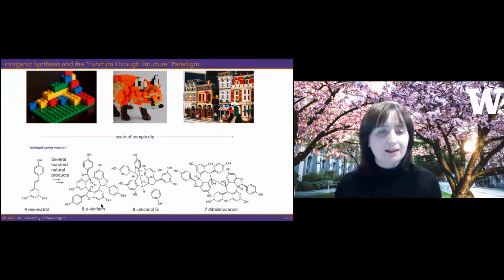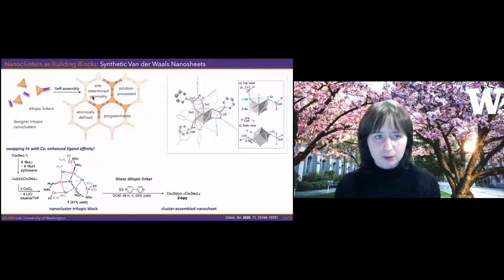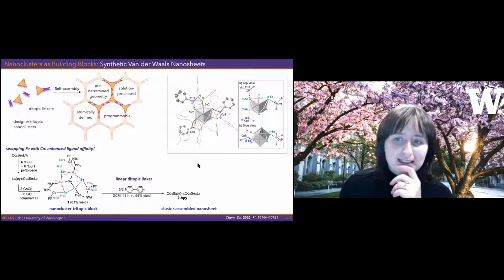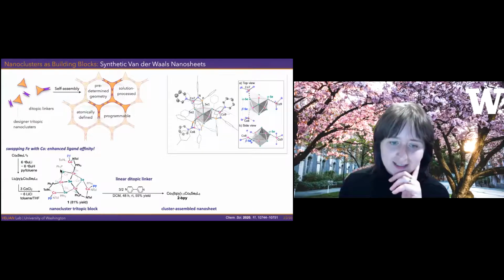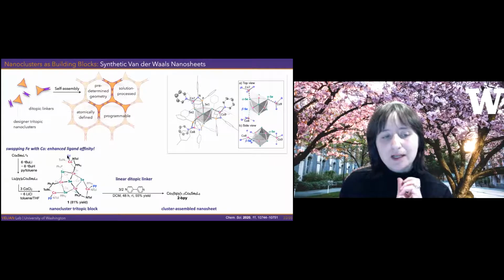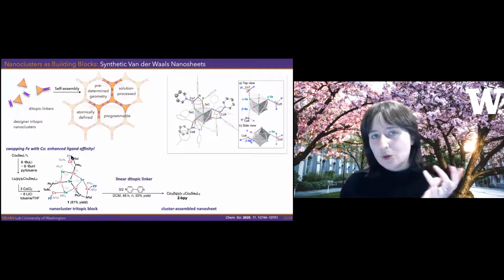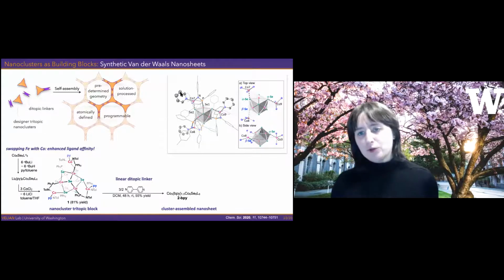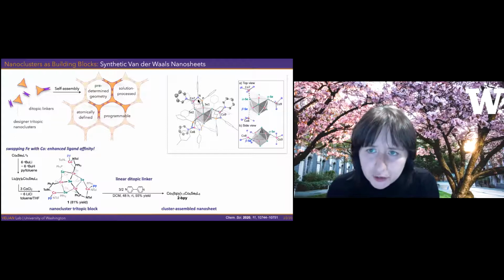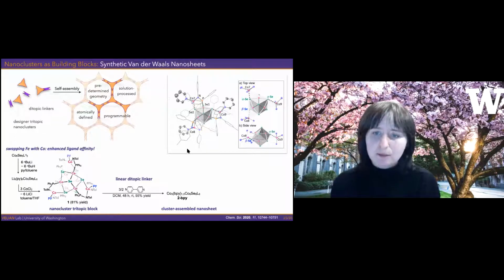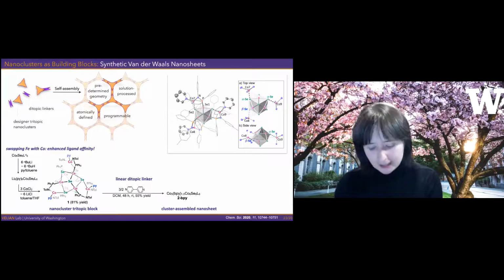And so we really want to tackle that in inorganic synthesis, and we want to put our clusters to use in that sense. As a last example of how we can swap these edge sites to achieve a function that we target, I'm showing here the tricobalt cluster. So essentially now you have cobalt on the core and cobalt on the edges. The reason we swap to it from other metals is that now the cobalt binds more strongly to other ligands, for example, a pyridine. On the right side, I'm showing just the crystal structure of this molecule, in which you can see that the cobalt binds 3 pyridines more stably than the iron, which has a lower affinity for ligands. And we thought we can harness this to build nanomaterials.